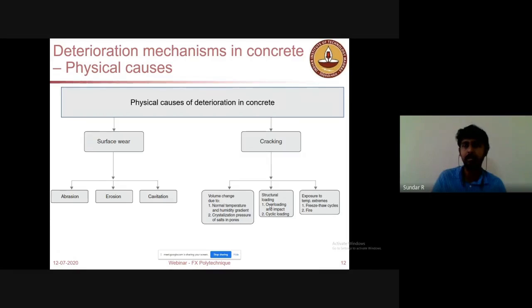Similarly, there is cracking due to the crystallization of salts. These are deteriorations where no chemical reactions happen inside the concrete, and adequate warning is given through cracking or surface wear. So this physical cause of deterioration can be dealt with much more easily, with caution, by providing enough resistance against surface wear and cracking, or even by making an impermeable concrete cover, which we will see later.